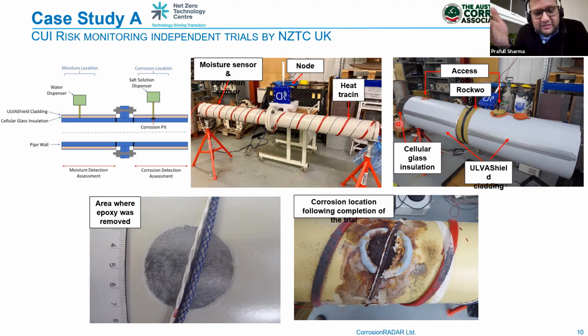It's basically a radar signal, the same radar signal which is used in spacecrafts or satellites. We pass similar signals into the sensors and detect where the water is touching the moisture sensor. But it does not mean that the pipe is getting corroded. It just means that the pipe is getting subjected to a corrosive condition, and hence it is a higher risk. So this is a risk monitoring technique.